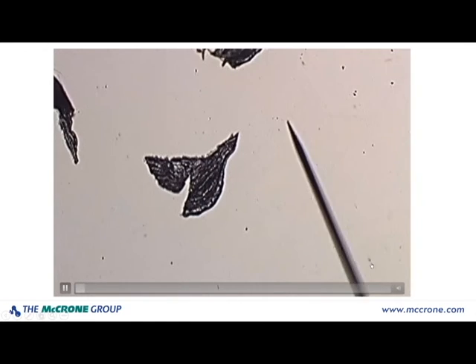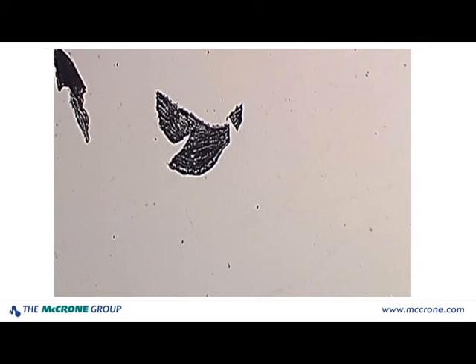This next video here, we're going to take a look at the harder plastic pieces. So here I have the plastic shavings, and again I'm going to cut smaller pieces. This time I'm using a 45-degree microblade, and now I'm going to switch back to my tungsten needle to move these smaller pieces and relocate them to a different area on my slide so I have room to manipulate it with my glass wedge. I'm really going to try to make sure that these smaller pieces fall between 200 to 150 microns, if not even less than that.